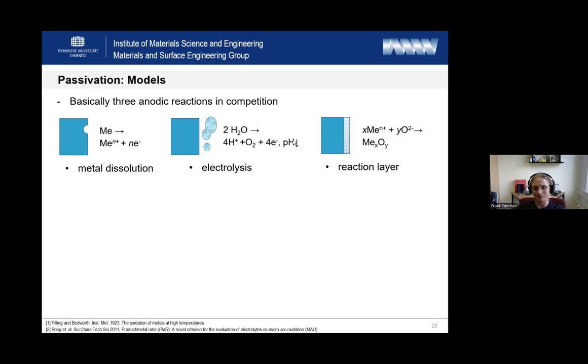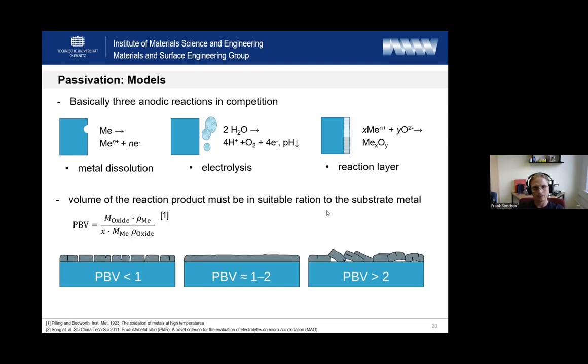And if in case that you chose a suitable electrolyte, this will lead to the formation of an electrically isolating reaction layer. So your metal ion reacts with the electrolyte to form an oxide. And in best case, this metal oxide is electrically isolating. But if this metal oxide is electrically isolating, it's not the only request which must be fulfilled. The volume of the reaction product must also be in a suitable range to the substrate metal.